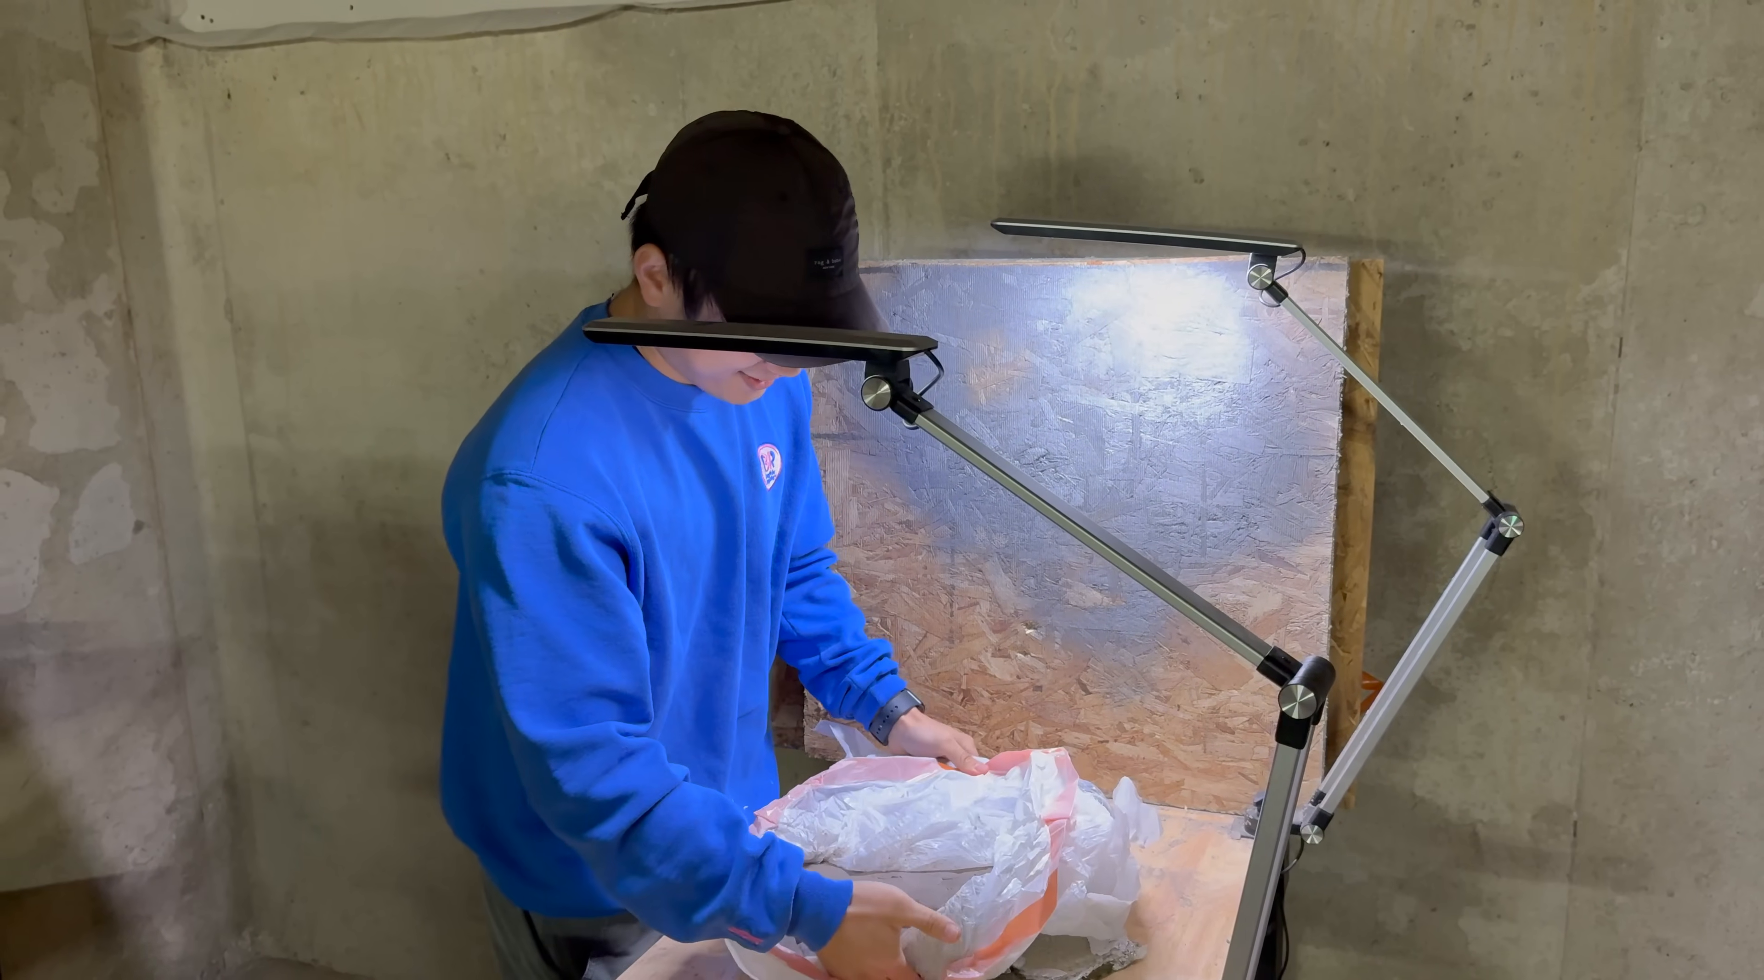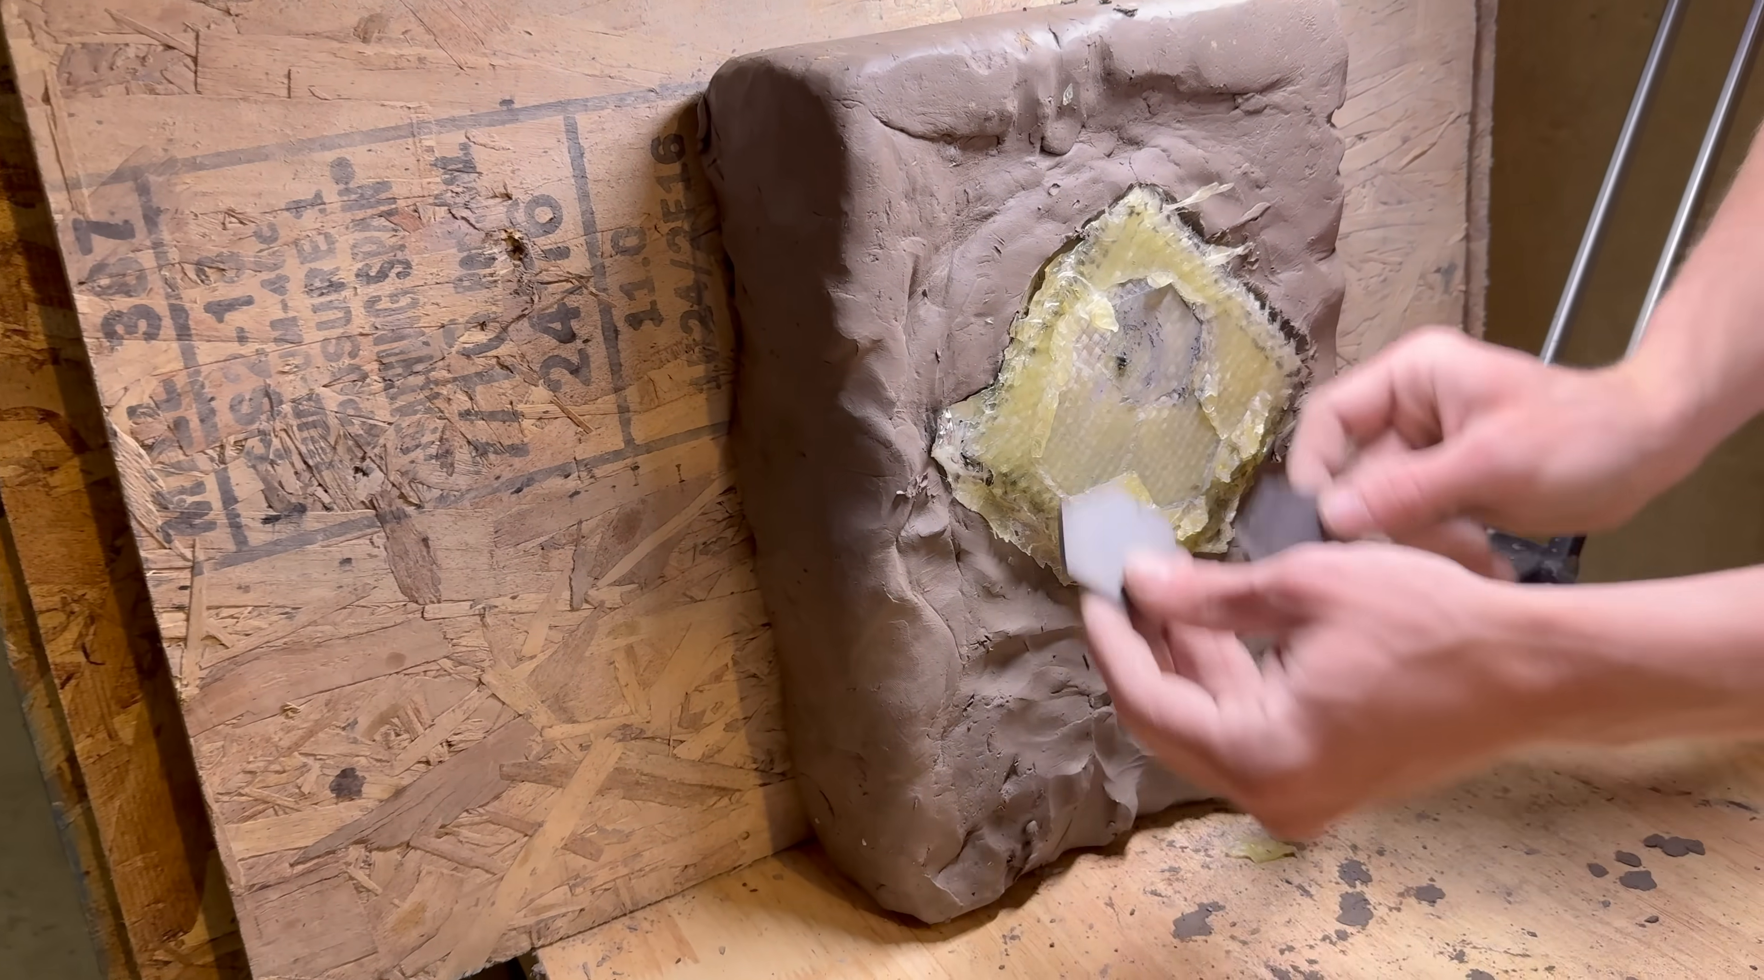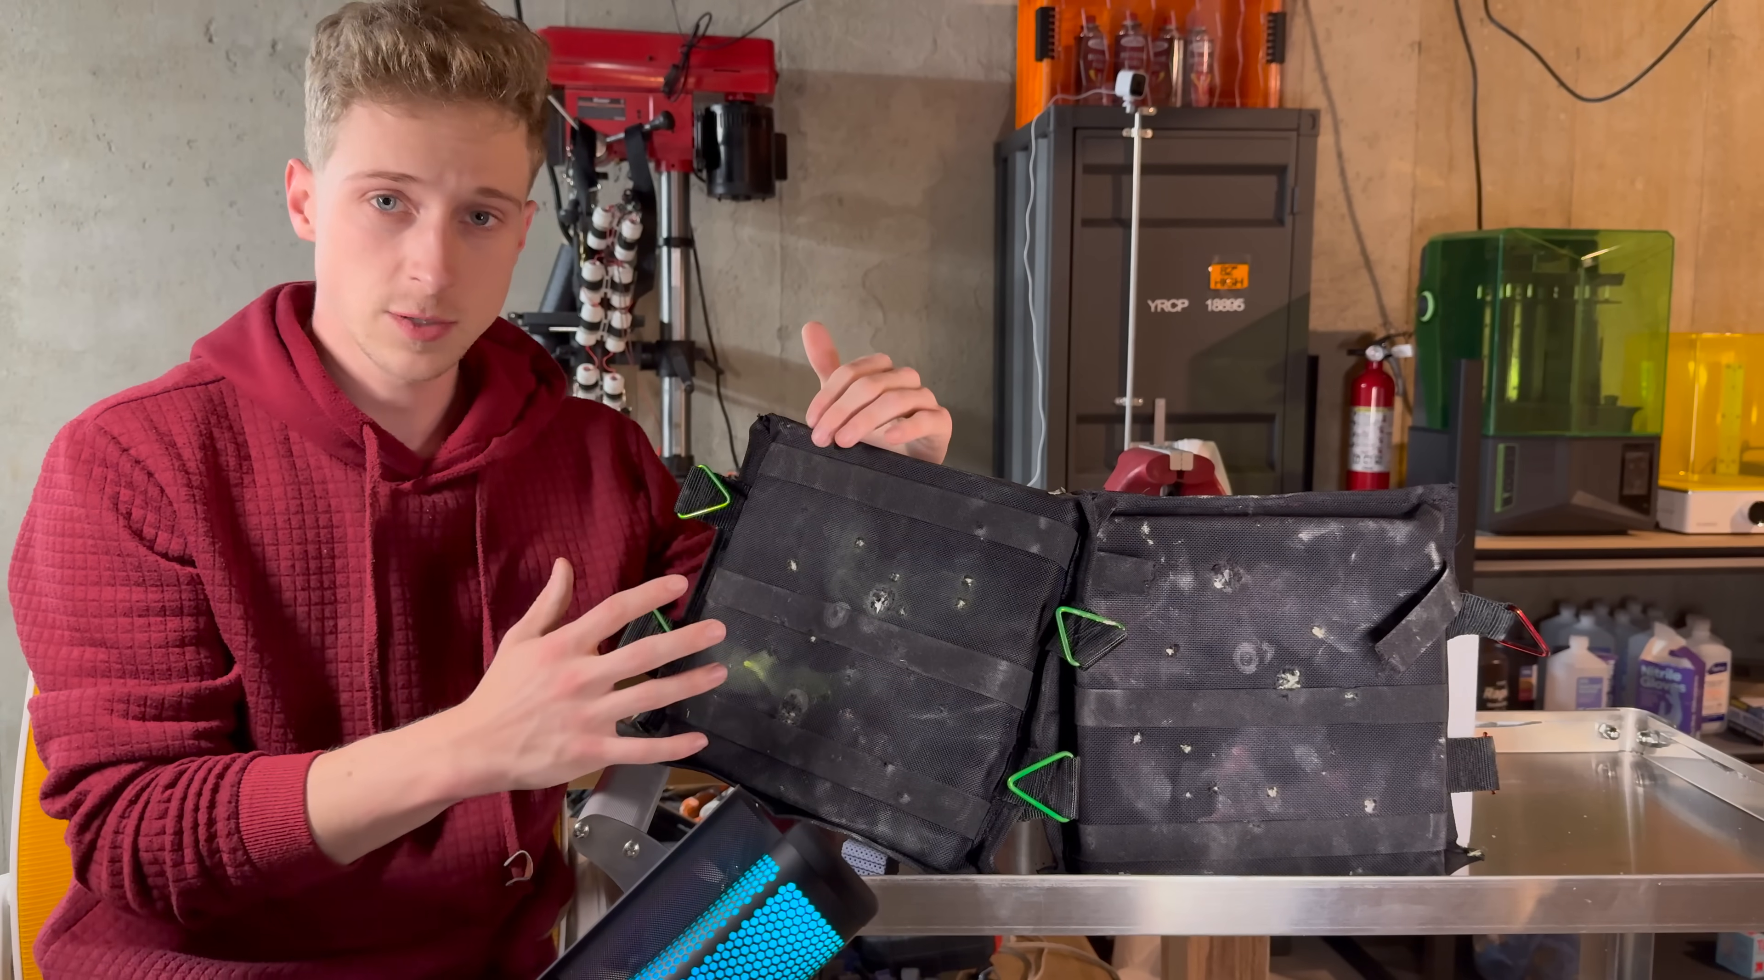This is henchman number two. John is unpackaging the block. So a lot of times you can just use standard epoxy. But what happens is it cracks. So if you look here I'm shooting a plate with a 5.7, just testing these adhesives. And I've got some silicon carbide tiles. And you'll notice with a traditional regular strong epoxy, it pops right off. It breaks. That impact is too strong. It just snaps. And your parts go flying everywhere. So you can do a different curing process and additives to make this much better at handling those impacts. Yeah, I know. It's legitimate goon work. You're fired.